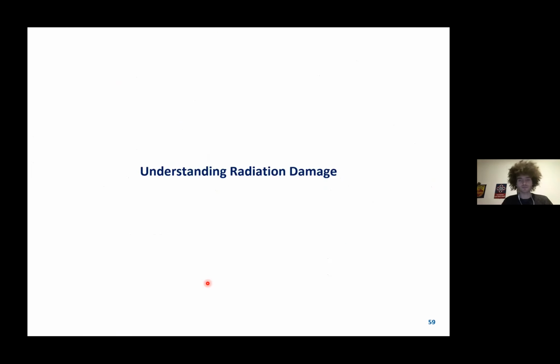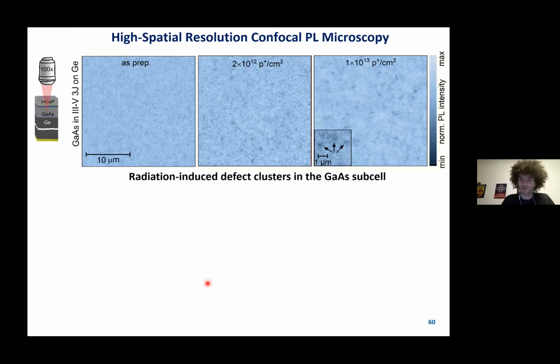All right. So now let's take a step back and look at the radiation hardness of the III-V triple junction, right? So there, if you remember the EQE I showed, the gallium arsenide middle cell degraded, okay? So now I looked at this gallium arsenide middle cell a bit more closely, this time using a confocal PL microscope. And here on the left is an image before irradiation. Okay, this is an epitaxially grown gallium arsenide layer. We would expect a very homogeneous PL.